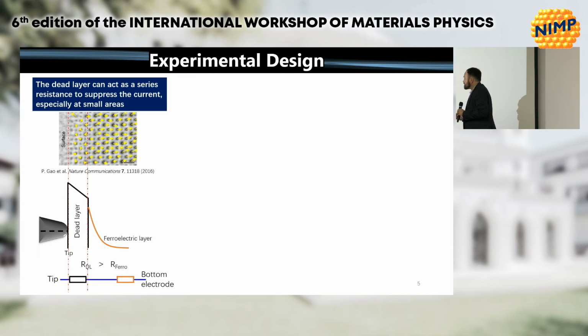On top of that, it's been reported that the dead layer can be effectively squashed with force. So you can squeeze it a little bit by applying a force with a tip. The dead layer basically isn't going to be beneficial for a ferroelectric memory device. It's going to suppress that current. So if you can make it a little bit thinner, you might be able to tunnel through that and enhance